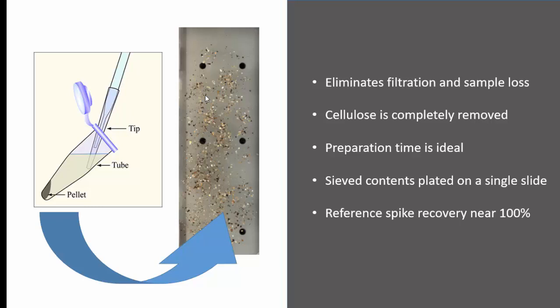So this is an oversimplified cartoon showing a micro centrifuge tube, but it would be the same for the larger 50 ml tubes that we used. After centrifuging the final sample, all the material is compacted in the pellet because we didn't use any density separations. Then we use a micro pipette to pull off all the liquid from the sample, getting as close to the pellet as you can.